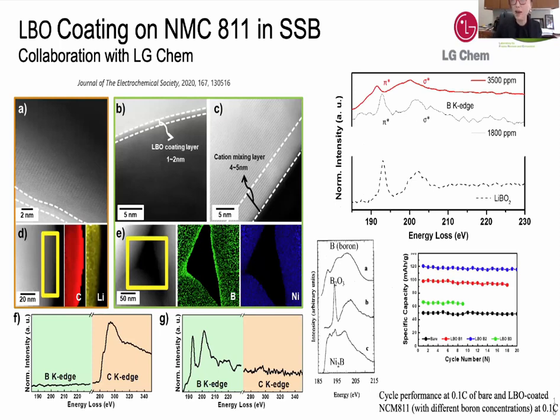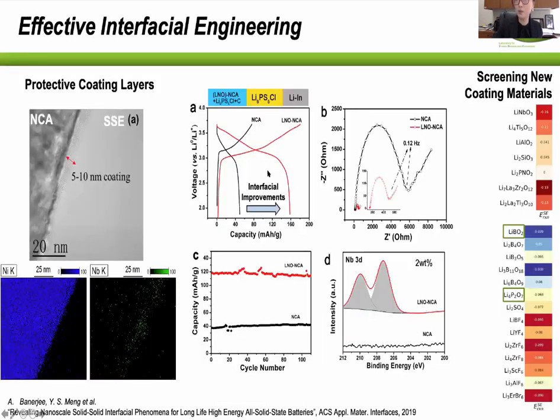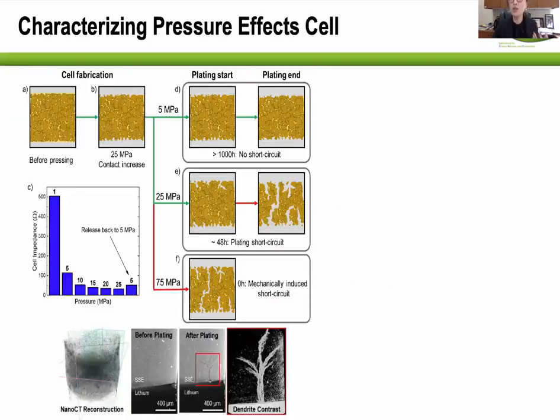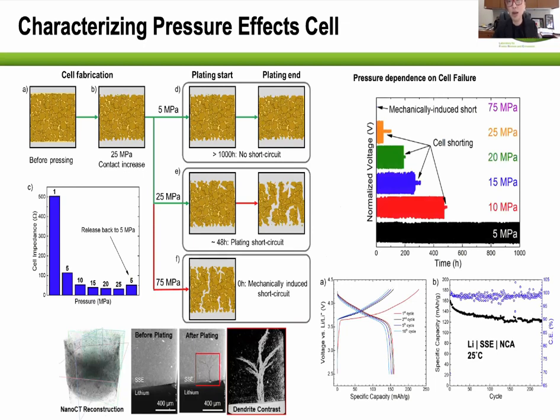You can do it, but I want to say all these cycling numbers we showed you here, critical current density is like 0.1 milliamp per centimeter squared, right? So if you wanted to really cycle lithium metal in solid state batteries, pressure effect is also unknown. I will tell you, we know so little about lithium metal's mechanical behavior. It was a surprise to many people. Actually, lithium metal needs to be cycled at a relatively low pressure, because plastic deformation of lithium happens severely if you go to high pressure. So for solid state devices with lithium metal as the anode, you cannot put 20-25 megapascal. You actually have to release the pressure in order for it to cycle. Again, the cycling current density is only 0.1.